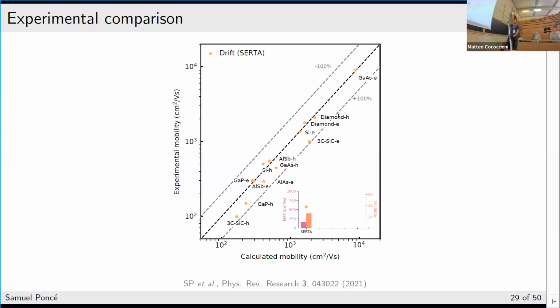If you compare to experiment, you have here the calculated mobility versus the experimental one. If you are on the line, it's perfect agreement. Note that this is a logarithmic scale, and basically the dashed lines are a difference of a factor 2, so it's 100% difference. You can see that in many cases we overestimate experiment, and this is actually expected because here we have only included the interaction between the electron and the lattice. But you have other scattering mechanisms: ionized impurity scattering, defects, and so on. So when you are comparing to experiment, you always expect that you will overestimate with respect to experiment.